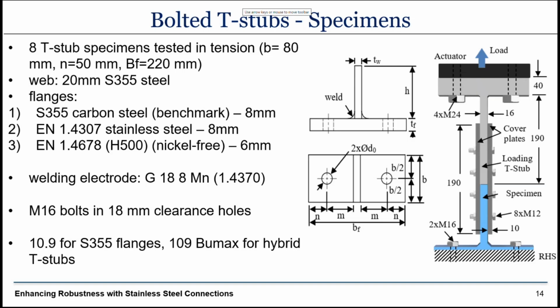We also did some tests on benchmark T-stubs with carbon steel for both flange and the web. So the flanges were either S355 steel with 8 mm thickness for the benchmark specimens, 8 mm in EN 1.4307 stainless steel for the conventional stainless steel grade that we used, and 6 mm for the novel stainless steel grade. We used the welding electrode that was recommended by the company Outokumpu that donated the specimens.